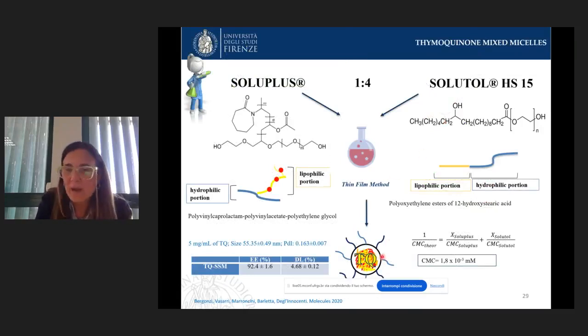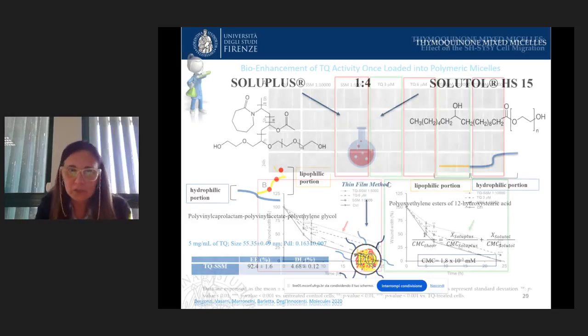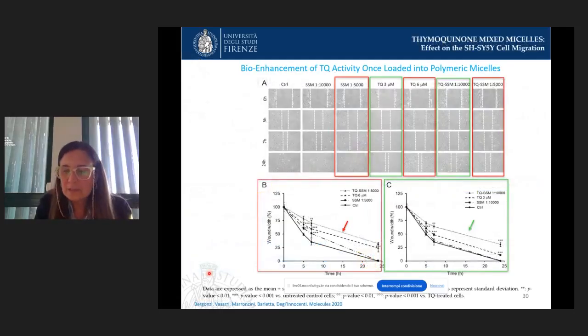In this case, we produced polymeric micelles using Soluplus and Solutol in the ratio 1:4. Both polymers are amphiphilic, and the hydrophilic portion is represented by polyethylene glycol. These polymers are solubilizing agents, but Solutol is also a P-gp inhibitor. The micelles have a good dimension, about 50 nanometers, and high encapsulation efficiency with respect to thymoquinone. We tested these micelles loaded with thymoquinone in neuroblastoma cells to evidence the influence of the formulation on the inhibition effect of thymoquinone on cell migration.